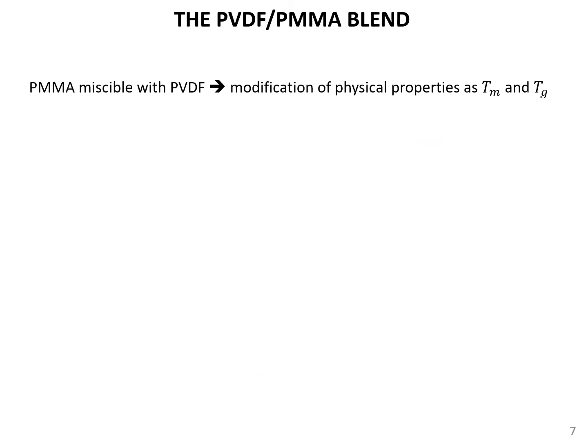To develop the PVDF blend, we selected PMMA in this investigation because most of the literature has already mentioned that PMMA is miscible and can cause modifications, particularly on the melting temperature and the glass transition.